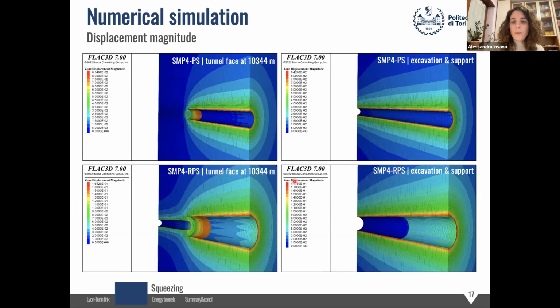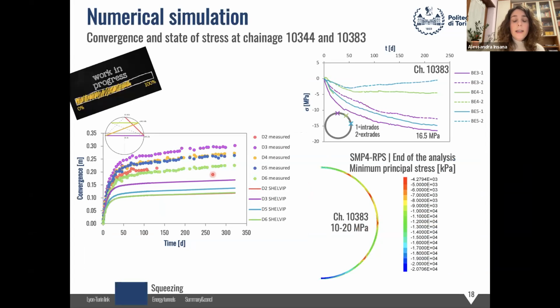So we see that the maximum displacement obtained is about 17, 18 centimeters. Of course, these sections are extensively monitored, so we have the convergence data. So we see here the results of the monitoring, the convergences in the direction highlighted here in the picture. And with the parameters that we have shown, the continuous curves are the ones obtained. So we are still underestimating a bit the convergences.